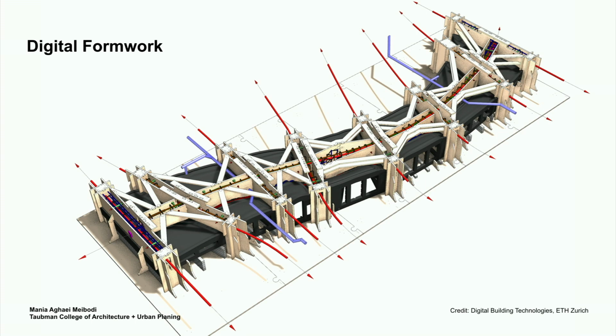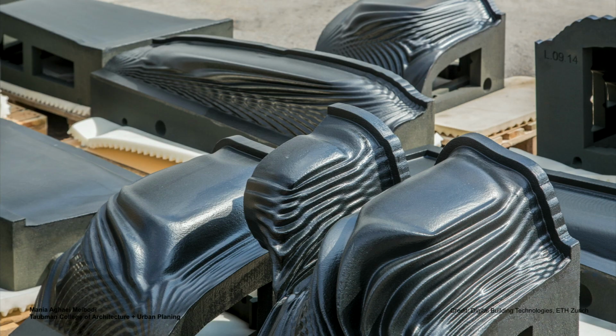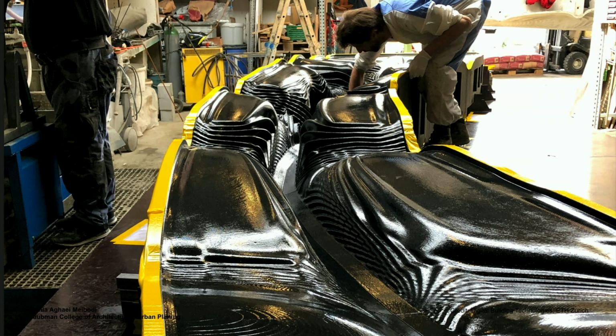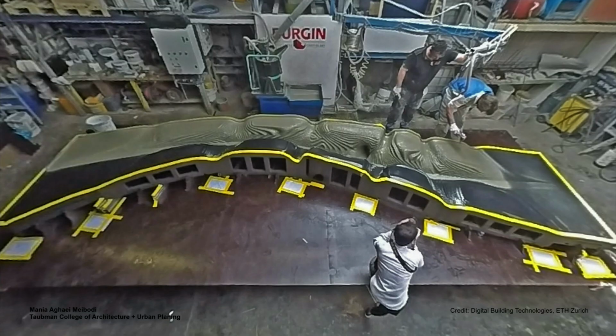What you see here is the formwork segment. As you may observe, it's made of many puzzle pieces of different parts: the CNC plywood section, the rebar that was bent previously, and the 3D printed formwork itself in gray. Here you would see the 3D printed parts. We had more than 181 3D printed formwork pieces that came together so perfectly to create one segment for a concrete element. Then for that segment, the glass fiber reinforced concrete was sprayed on the formwork, from which a 20 millimeter shell of concrete surface was created.